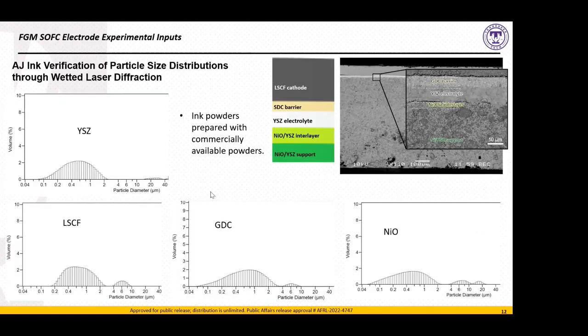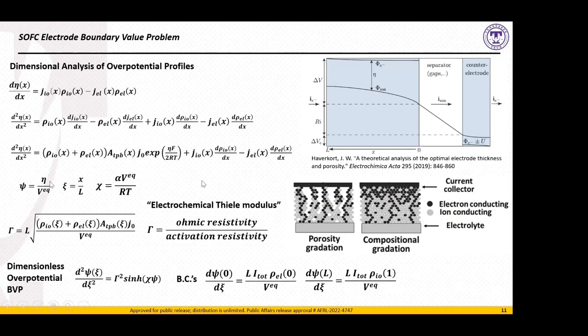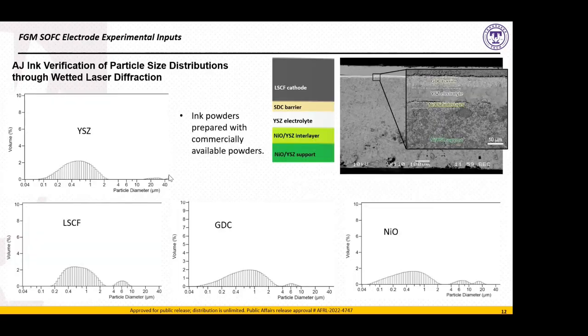Now, looking at some of the inputs that we need for our problem, and here I'll just again point out, we have to define this ionic and electronic resistivity. We have to define the area of the triple phase boundary, which is the boundary at which the oxygen and the hydrogen can combine and then desorb in the form of water. And we have to also define our exchange current density, which is the J naught term. As we think about this, we think about forming a porous conductor that is formed of various grain